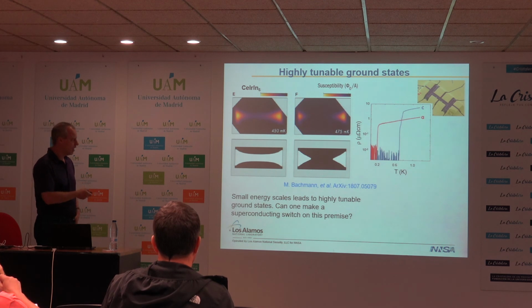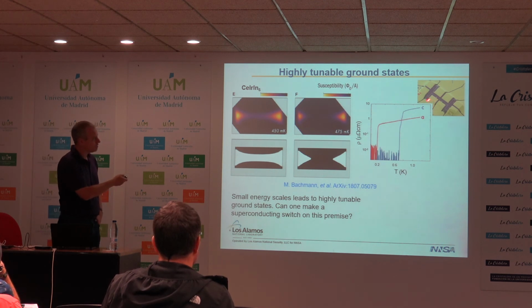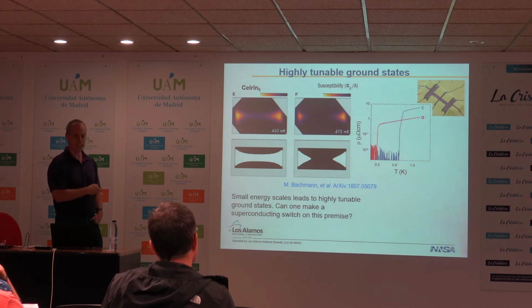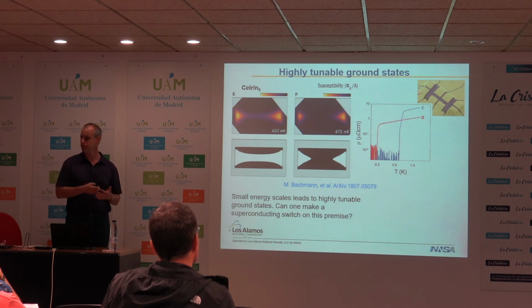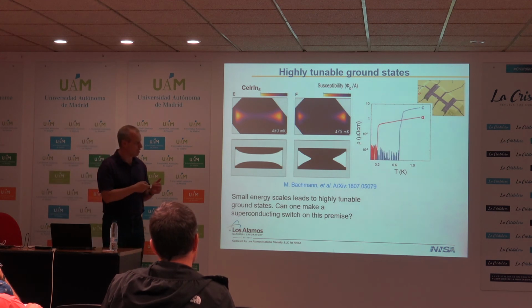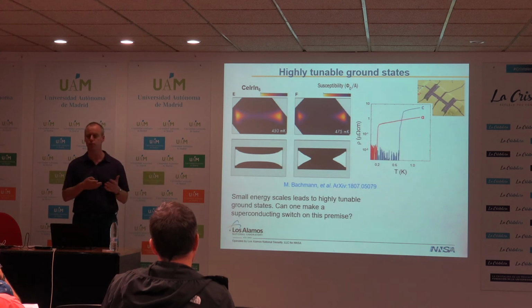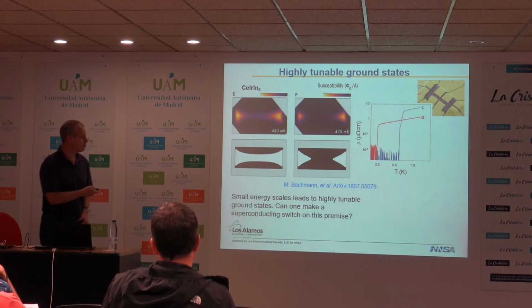And in fact they go on to make one of these devices here where you have a c-axis resistivity leg and an a-axis resistivity leg. So cut from the same material, you can vary Tc by a factor of 3 in the system. So the hope is that we can put devices like this, perhaps on a piezoelectric, and then be able to drive and modulate the superconductivity in such a system.